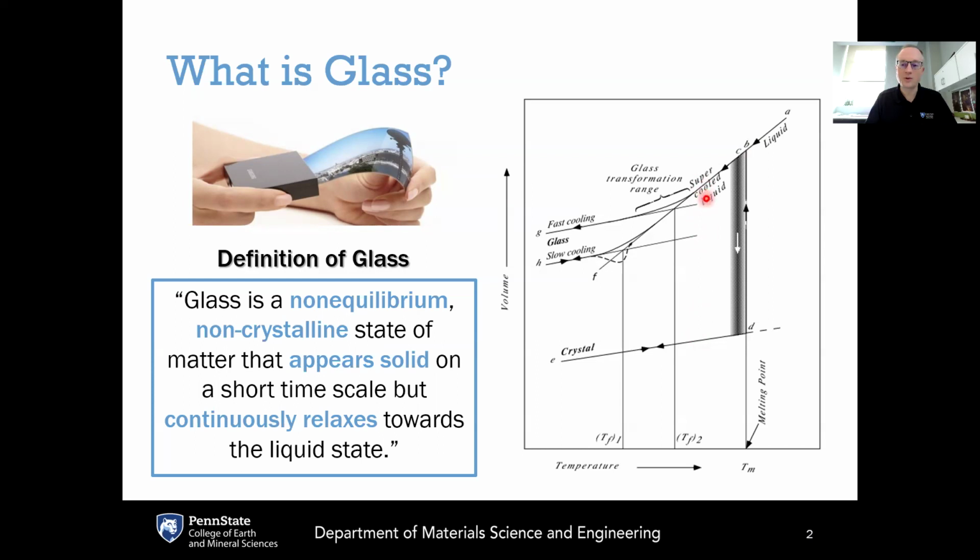The supercooled liquid is not the equilibrium phase, but it is a metastable equilibrium phase. Metastable meaning that it is unable to lower its Gibbs free energy anymore unless it undergoes a drastic change in structure, or in other words, undergoes a phase transition in order to crystallize.